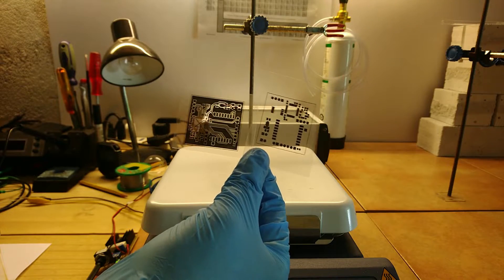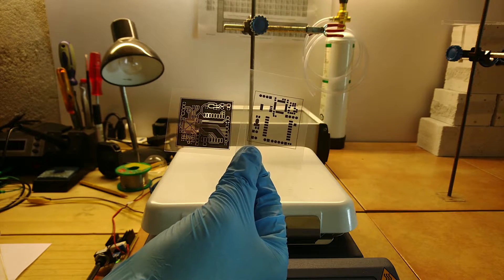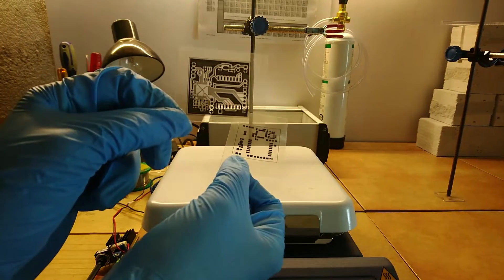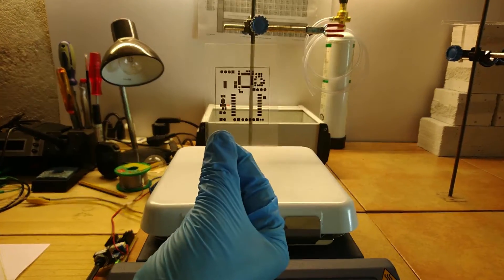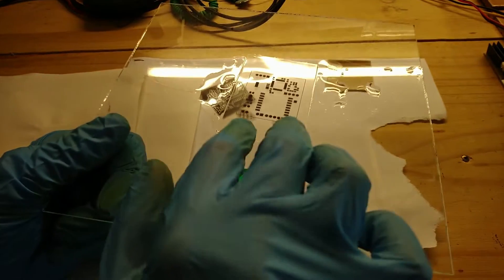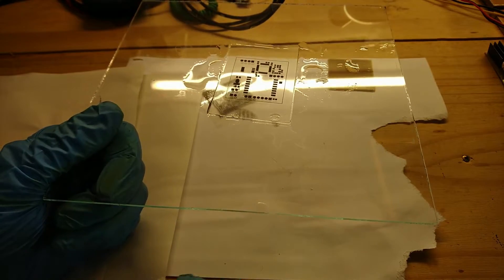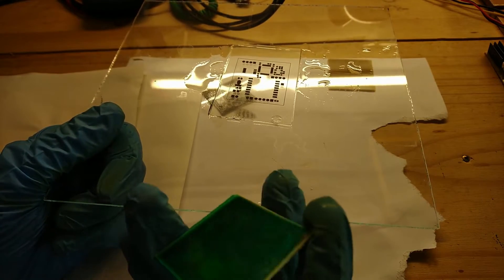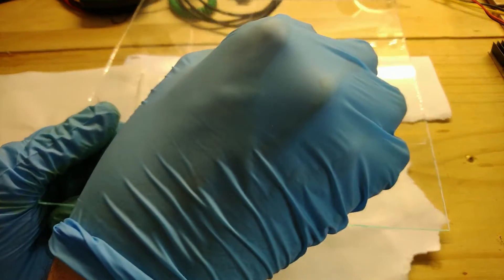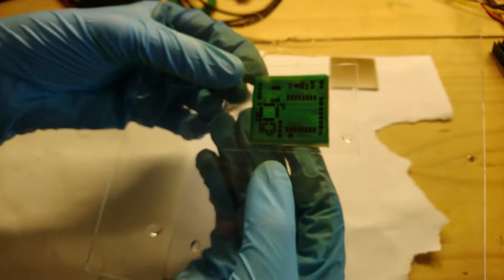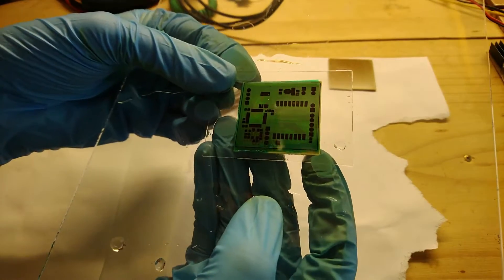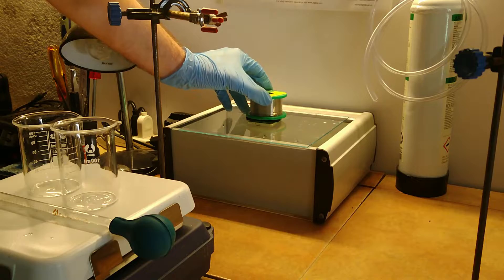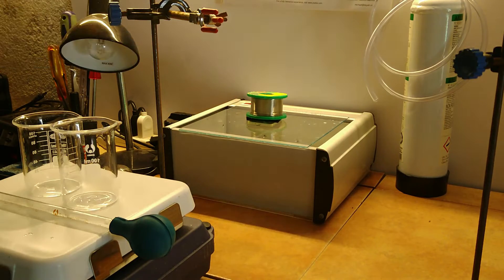You need to print a second mask from your CAD files for the solder mask apertures. Note that the solder mask uses a negative photoresist, so what is exposed to the light is what remains. Exposure is usually faster than positive photoresist, a couple of minutes are enough, at least with my UV lamps. After that, you need to leave the PCB in the dark for one hour.